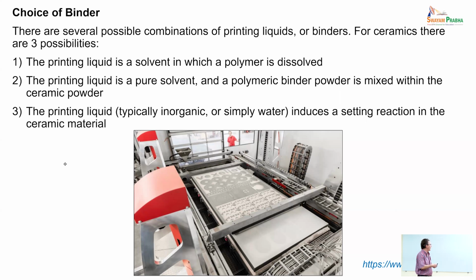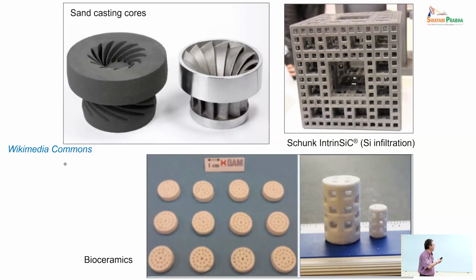The liquid that you're jetting from the nozzle can either be this solvent-containing binder, or it can be just a solvent, and you can put binder particles together with the ceramic particles, and the solvent will locally dissolve the binder particles, joining the ceramic particles together. So you can see, for instance, that people have been using this technology for making some casting cores.